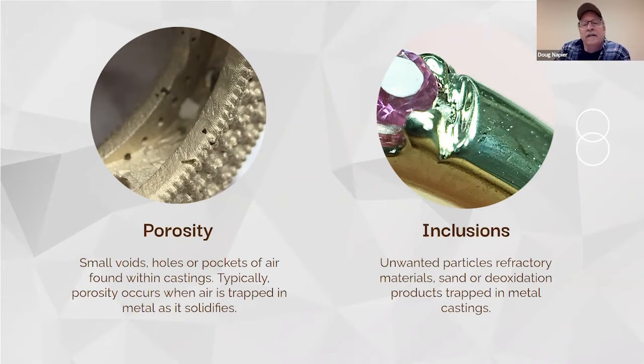So it looks like a good piece, and then you go to clean it up and polish it, and all of a sudden you've got these little pits in a surface area that you can't get shiny. It's embedded all the way through, so it's not just on the surface, but it's all the way through your metal. And there's ways to get around porosity. You can get burnishers and porosity beaters, what they call them, and take that metal that's around it and smear it over those pits so that it'll hold a high polish. The metal is still embedded with those small areas, but you can figure out ways to hide them. And that's what you would do with the porosity.